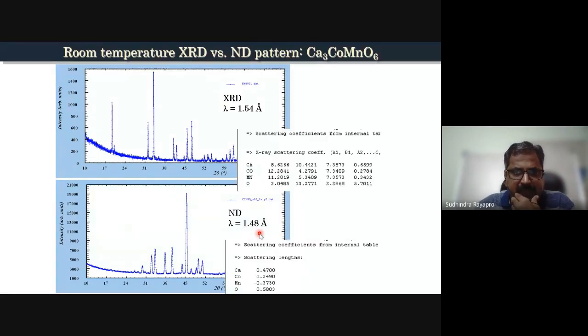And the main reason, as we have seen above, is because of these scattering coefficients in case of X-rays and neutrons. If you observe this carefully, calcium, cobalt, manganese, which are heavy elements compared to oxygen, the scattering is high, and for oxygen it is low compared to this. But in case of neutrons, you have almost identical scattering factors. In fact, oxygen is the strongest one. So if you are working with oxide materials, you have to choose your radiation carefully so that you can use the best radiation source for getting the best values.